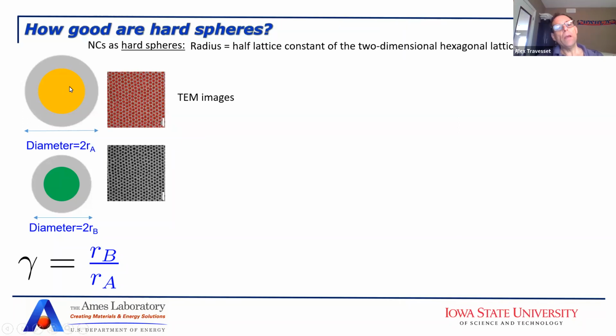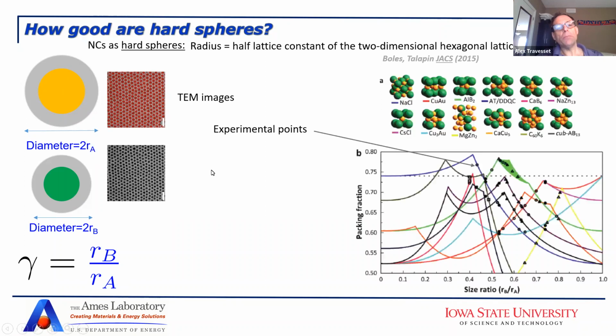Then you compute these 3-dimensional plots, and you do an experiment, and you realize that there is a correlation between where the packing fraction is maximum and where experimentally these lattices are found. So for example, if you have a ratio of diameters of 0.8, typically you will get magnesium zinc 2, which is the one that has the maximum packing fraction here. And this is already something.